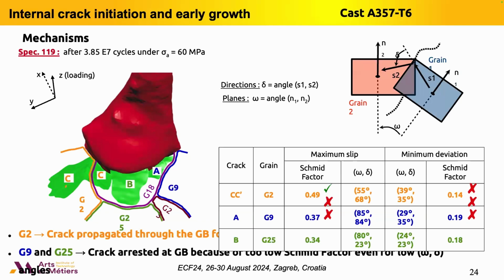So in fact, in the literature, we know that when a crack interacts with the microstructure, the crack is able to tilt and to twist to change its propagating direction. So we have computed in the neighboring grain the 2 different possible configurations: either the maximum Schmid factor, corresponding to the maximum possibility of slip, or the angle of the twist and tilt corresponding to the minimum deviation. And we have observed, in fact, that the crack C, corresponding to the propagation in the grain 2, propagates through the grain boundary because it corresponds to the maximum Schmid factor, but not the minimum deviation. Each time you look at the minimum deviation of the tilt and twist angle, you do not obtain a high Schmid factor. So in fact, it is clear that the crack propagation is governed by the slip activity in the neighboring grain, and the crack doesn't try to minimize the tilt and twist deviation.